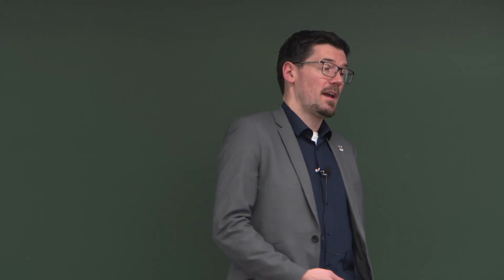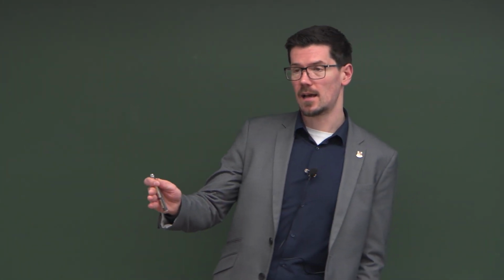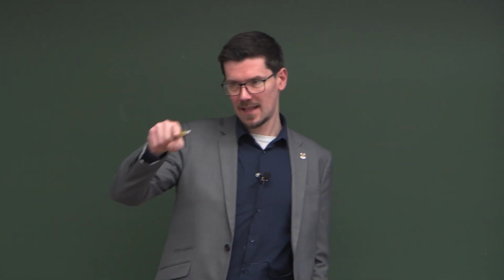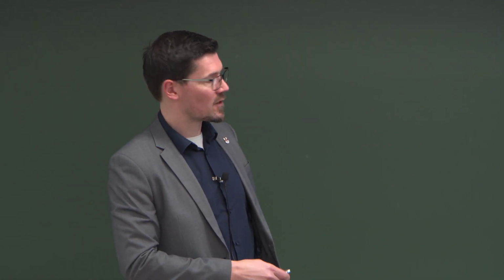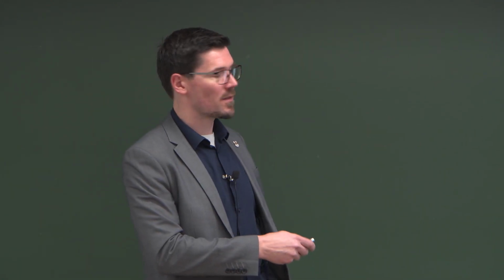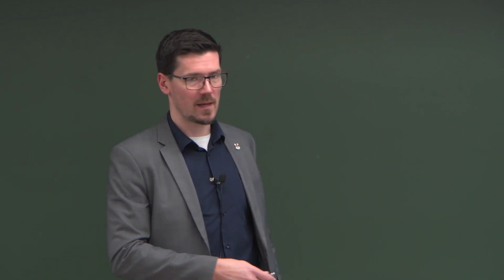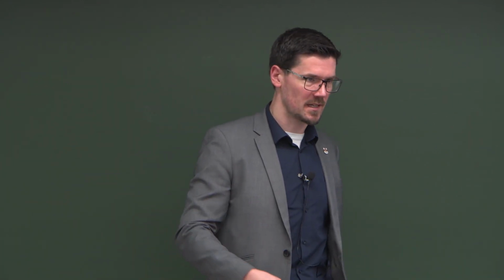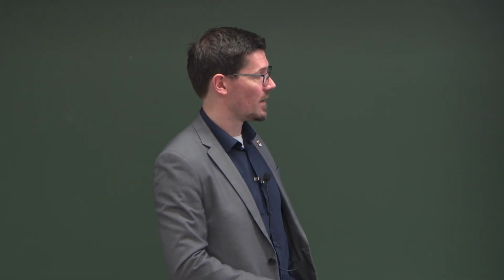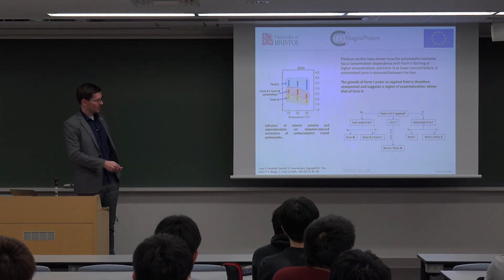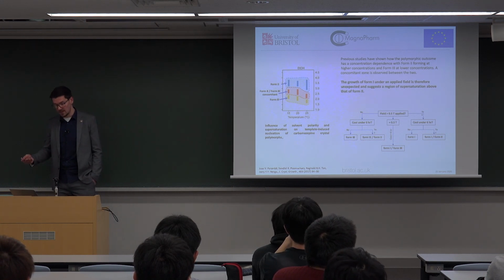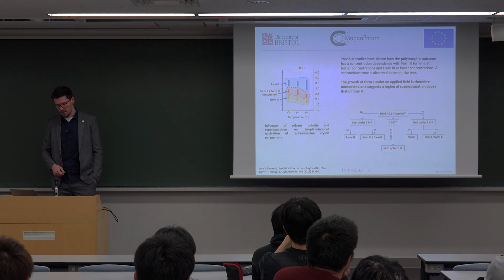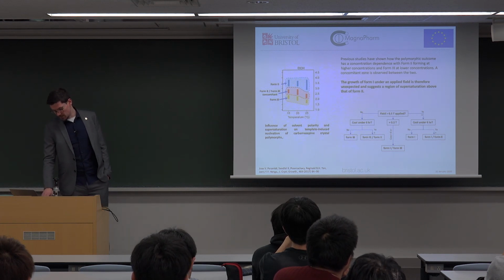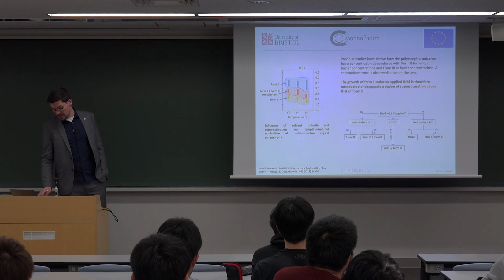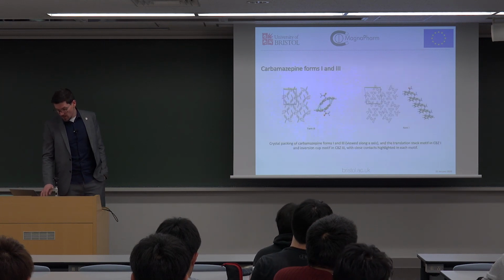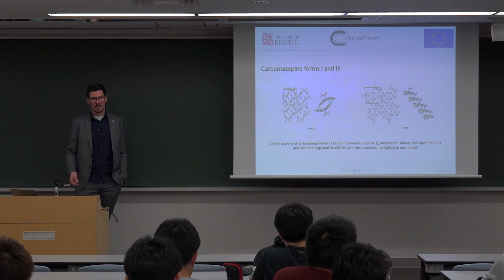So it looks like what we may have been doing is getting the suppression of crystallization into that little wedge again, and increasing the supersaturation beyond which they can do through just solvent-mediated means. We're suppressing the crystallization, increasing the supersaturation, and making form 1. This is just a flow chart of how we've been getting the different forms of carbamazepine. This is now 2 systems in which we've seen it work. A difference in the carbamazepine unit cells, form 1, form 3.